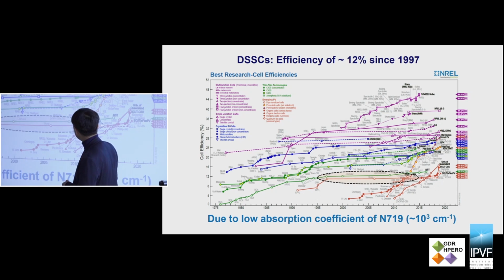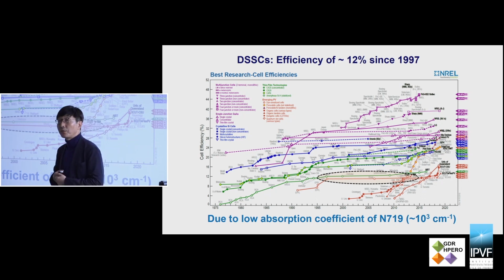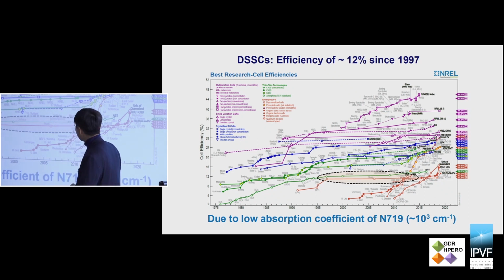After that, the efficiency is almost constant. The efficiency limitation of the dye-sensitized solar cell is due to the low absorption coefficient of the sensitizer. This is actually not organic, this is a ruthenium complex, so it is an inorganic sensitizer, but with a molecular structure. The absorption coefficient is usually one order of magnitude lower than the conventional semiconductor light absorber. So people wanted to find a better sensitizer to replace it.